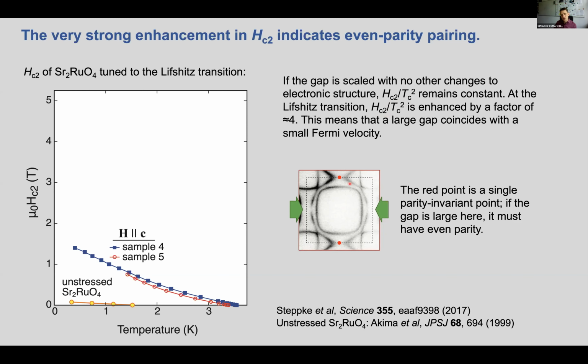That's highly suggestive because when we tune to this Lifshitz transition, the place where the Fermi velocity is smallest is right at this point, right at the Van Hove point. So this very strong enhancement in Hc2 tells us that we have a large superconducting gap right around this point. Now, the thing is that this point is parity invariant. This point is the same as this point on the opposite side of the Brillouin zone. It is a single Van Hove point. So if we had an odd parity order parameter, by symmetry, the gap of that order parameter would have to vanish at this point. So if we say that we have a large gap at this point, then it must be an even parity order parameter.